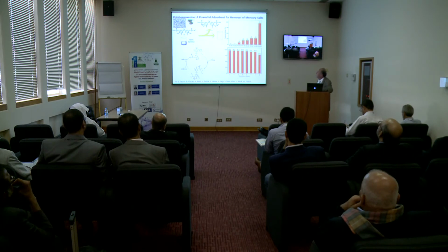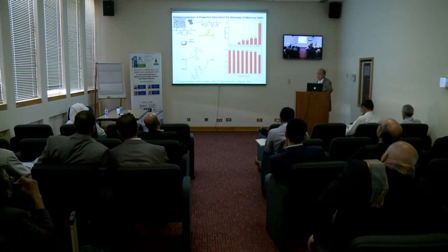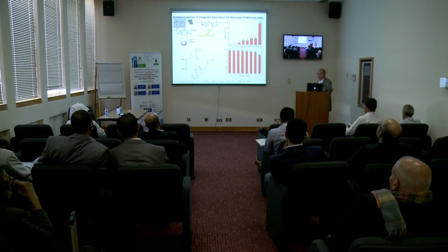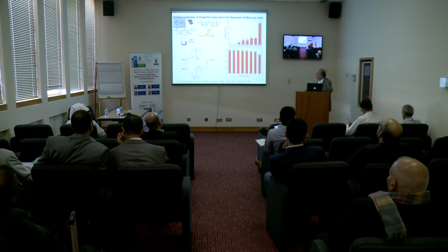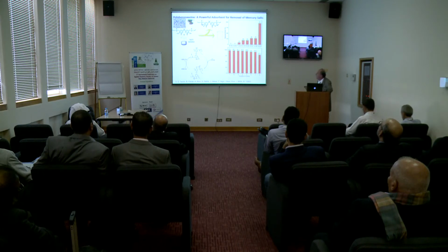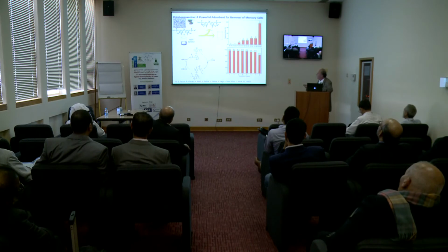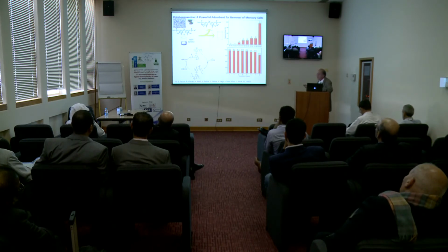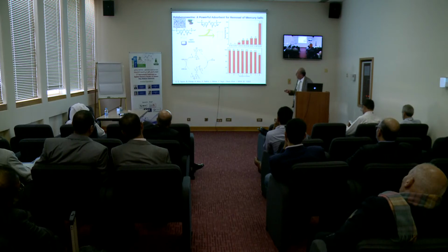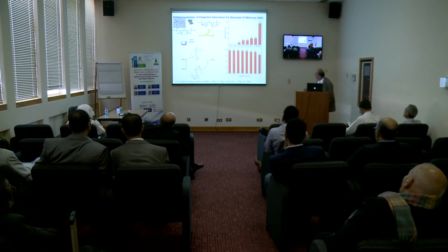Now we move to another application of environmental purpose. This is a kind of polybenzoxazine here, and it's a porous material. The surface area is, per gram, probably 500 square meter. If you have a solution containing mercury, if you add this porous system onto here, and it becomes clean solution there, because the mercury has an interaction with non-bonding electrons of oxygen as well as nitrogen, it's strongly coordinating. And the advantage here we have, you see that if you treat with acid, you recover back the original material. So it's a reusable one.